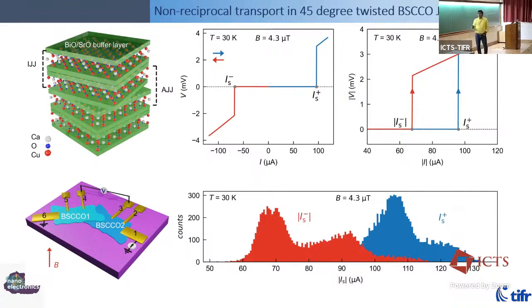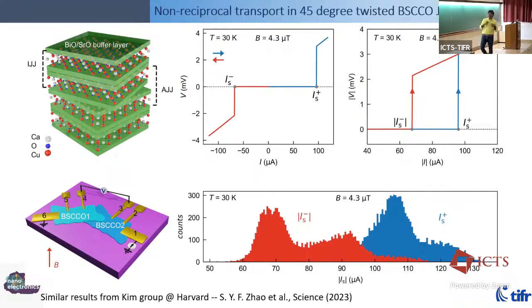So it's a Josephson junction, and Josephson junctions themselves are stochastic devices. If you take an aluminum Josephson junction and you switch it many, many times, it will not switch at the same current. That is not a bug of the device, it's a feature of the device, because the system lives in a well and you run it out by tilting the washboard potential. So when you switch it many, many times, this is some 10,000 switching events, you see that there are some multiple humps in this, but that's related to the physics of high Tc. I won't go into too much detail here, but I can talk later. But they are asymmetric. So this is what is called the Josephson diode.